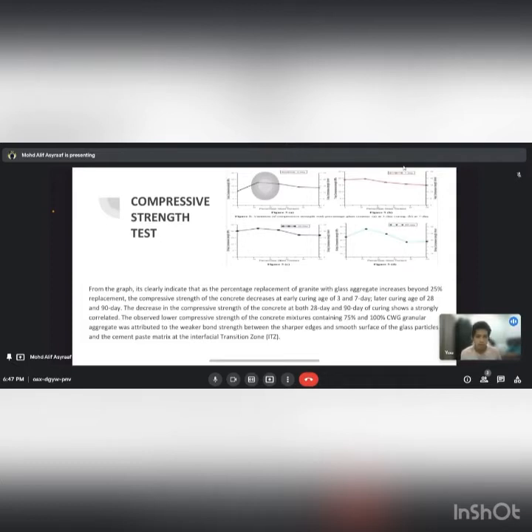Later, the curing age of 28 and 90 days. The decrease of the compressive strength of the concrete at both 28 and 90 days of curing shows strongly correlated. They observe lower compressive strength of the concrete mixture containing 75 and 100 percent glass aggregate was attributed to the weaker bond strength between the sharper edge and smooth surface of the glass particle and the cement paste matrix at interfacial